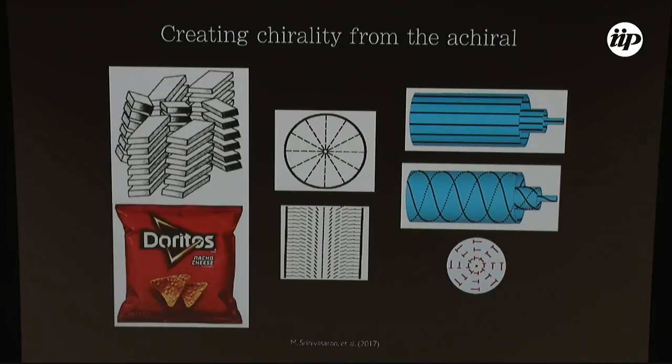But one thing about these discotics is that the K2 term, the twist elastic constant, is much, much lower than it is in standard nematogens like 5CB and things like that. So these have quite a high propensity to twist. If you imagine putting them in a capillary tube with homeotropic anchoring, normal nematics will just have this escape in the third dimension texture as their way to accommodate these boundary conditions.